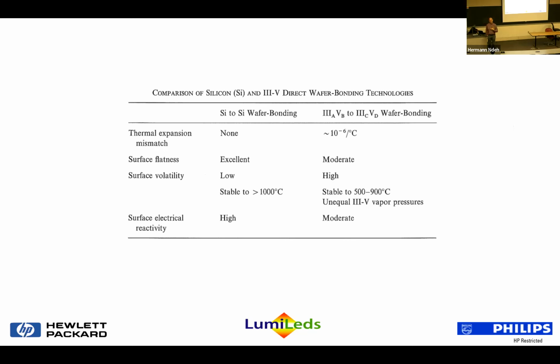about that. That being said, when we started on this work in the early 1990s, silicon to silicon wafer bonding was just being developed, but for the bonding of compound semiconductors or 3-5s there was maybe one paper published at the time on this. Some of the differences are that you have a thermal expansion mismatch when you're bonding two dissimilar 3-5 materials together. The surface flatness is nowhere near the atomic smoothness that you can get on a silicon wafer. The surface volatility is high, meaning you have to worry about decomposition, especially of the column 5s. And the electrical reactivity of the surface is also different. So you just can't take the same techniques that people have developed for silicon to silicon wafer bonding and apply them to 3-5.